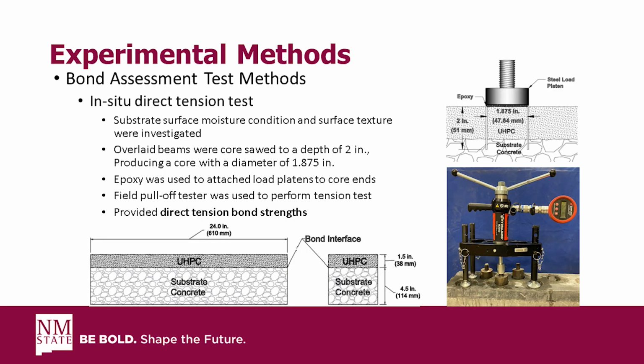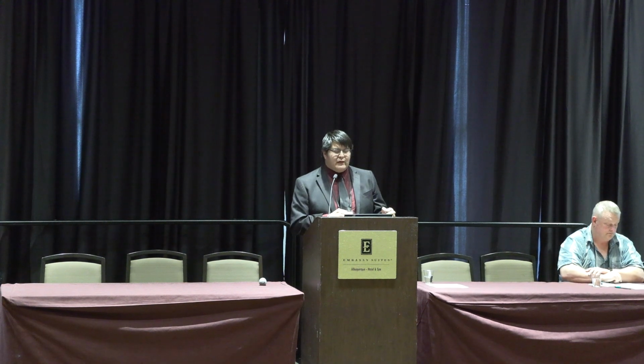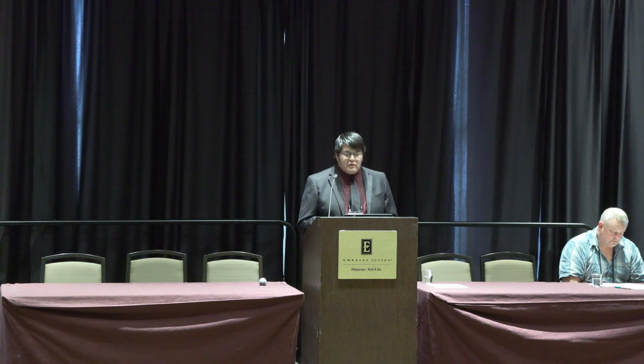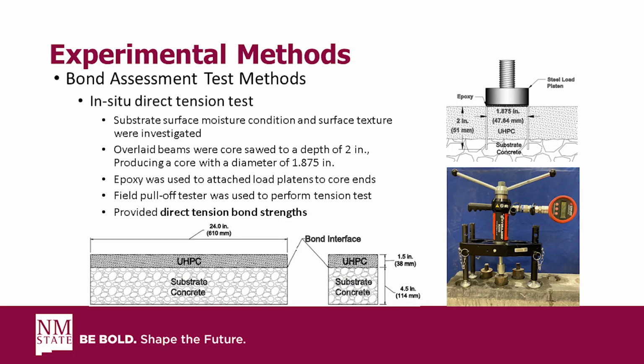Okay, so now going into the actual bond assessment test. Here we provided what we call slab specimens, but they're just small 6 by 6 by 24 inch beam specimens that have 4.5 inches of depth for the substrate concrete. And what we do is texture the top surface and then overlay that surface with a 1.5 inch thick UHPC overlay. You can see that in the bottom left illustration.